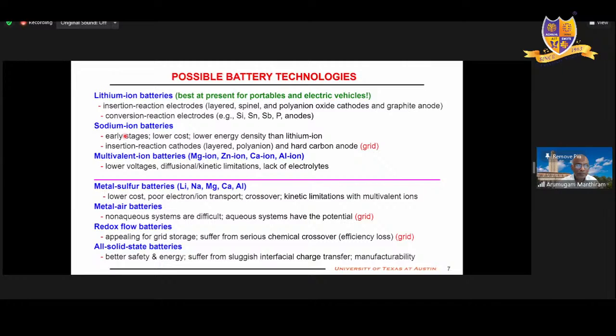I talked about sulfur. It has 10 times more charge storage capacity, but sulfur is a poor electronic and ionic conductor, and you start with the 8-membered sulfur ring that is insoluble in the electrolyte. Once the ring breaks slowly, you get these species. They are soluble in the electrolyte, so they go from this electrode to that electrode. That is a big headache. That degrades the cyclability. Lithium metal also has a mossy, dendrite kind of microstructure.